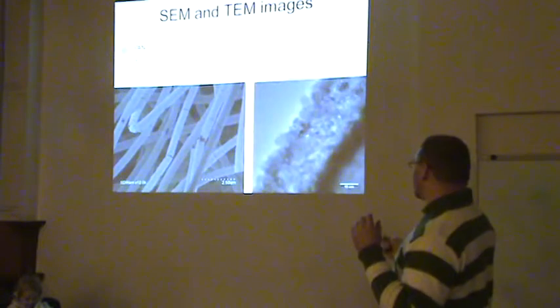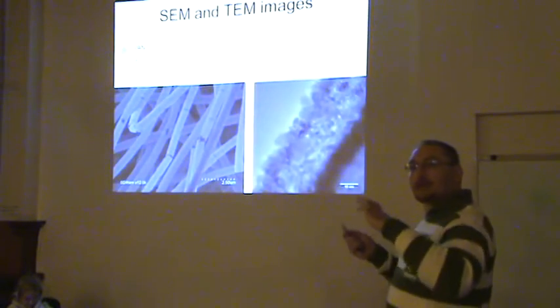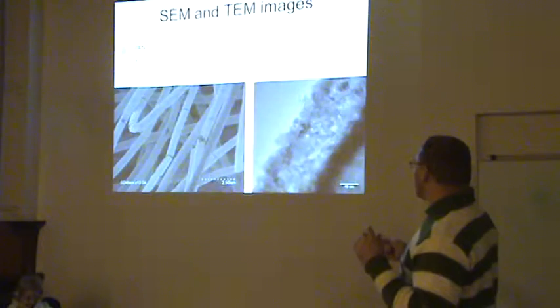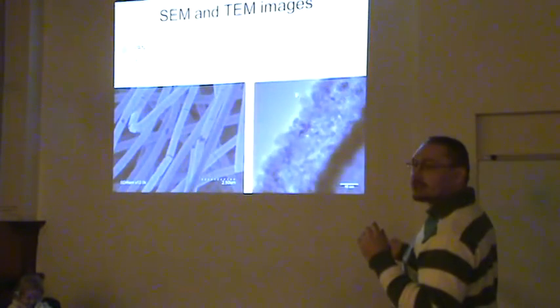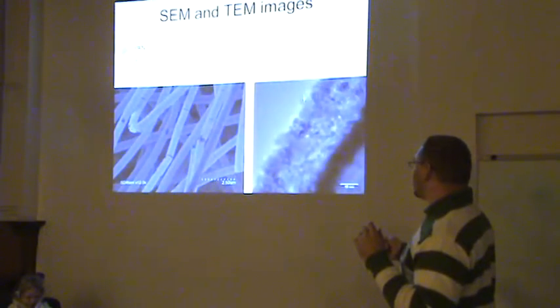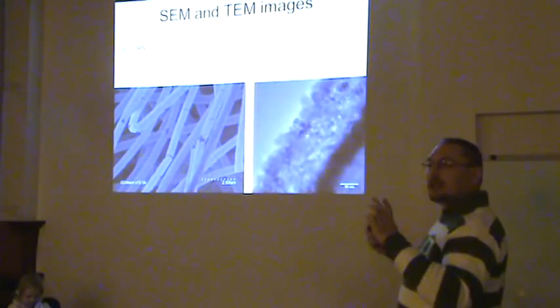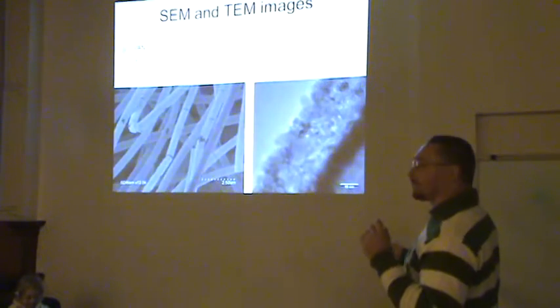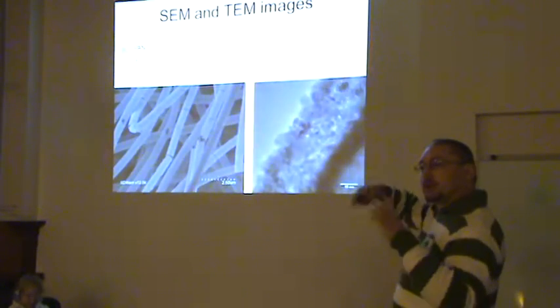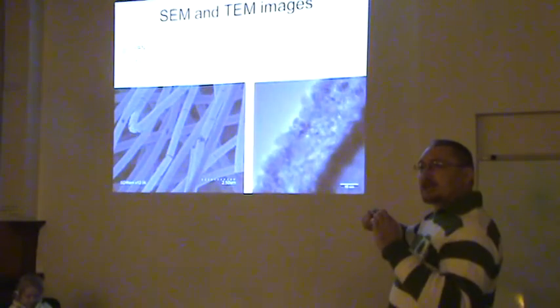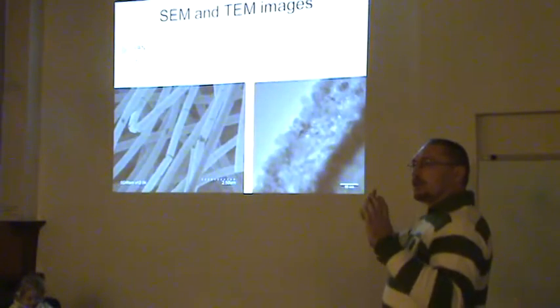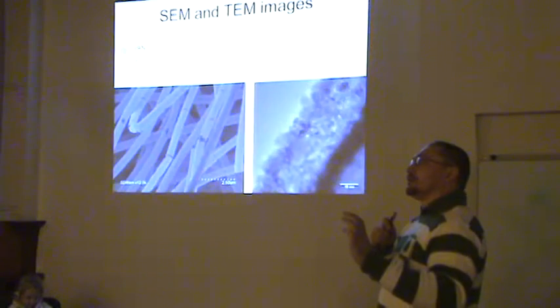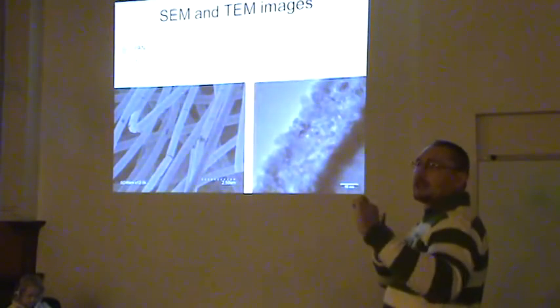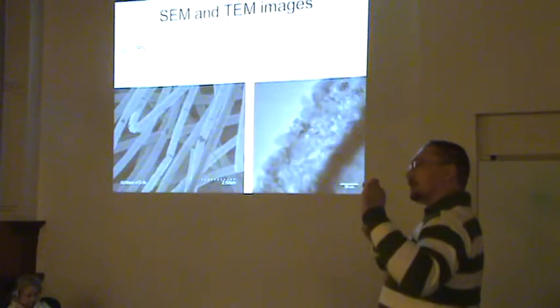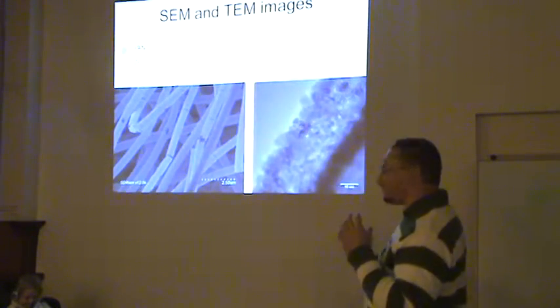With transmission electron microscopy, we can have better resolution, and we can even see single grains, single crystallites. So this dimension is about 9 nanometers, and if you take some analysis, you can calculate the number of the particles, and you can make a distribution. You can calculate the average grain size, and you can calculate how many crystallites with 9 nanometers, how many crystallites of 4 nanometers you have in the samples.